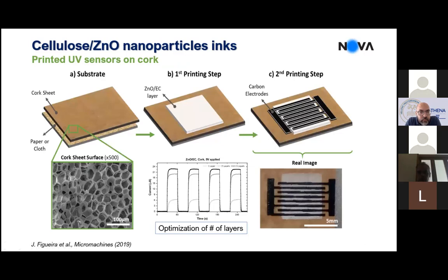Okay, so some examples. I will not spend so much time in order to keep us on time, but of UV sensors produced on cork. In this case, it's not paper, the substrate, it's another natural material, it's a cork surface, okay? And you have here some UV sensors, and you see the response. Of course, you need to adjust the thickness of the layer in order to maximize the response, because you see the surface. The surface is a very challenging surface, the cork. It's even more challenging than printing on paper.